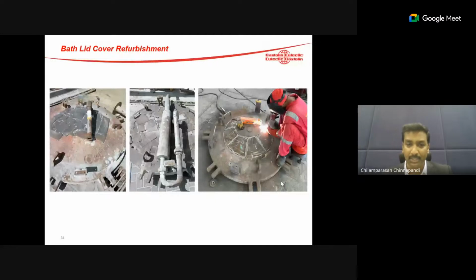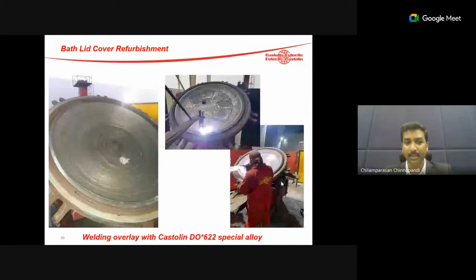We understand these applications. What we did: we checked the thicknesses, removed the complete damaged areas, and rebuilt it to the thickness required for this component. Then we did the repairing with our specialized welding overlay alloy called 622. It's a high nickel content electrode which has the highest elongation properties, and it can work up to 1000 degrees, so it doesn't react to thermal shocks. If the thermal shocks go up to 1000 degrees, it can come back as well. It's not going to affect it.